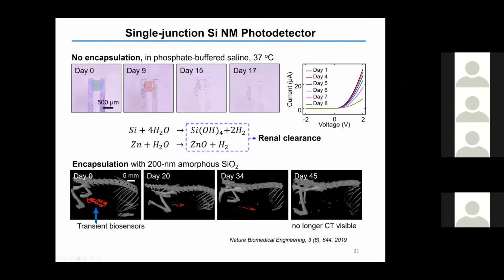Without an encapsulation layer, it takes around 2 weeks for typical bioresorbable optical probes to fully dissolve. Adding a 200 nanometer amorphous silicon dioxide layer can effectively prevent the penetration of biofluid into the active electronic components and maintain stable performance for 10 days before undergoing bioresorption. For the current device shown here, we use a doped silicon nanomembrane as a photodetector, which relies on a tunable laser as an external light source to realize spectroscopic sensing over a wide range of wavelengths.